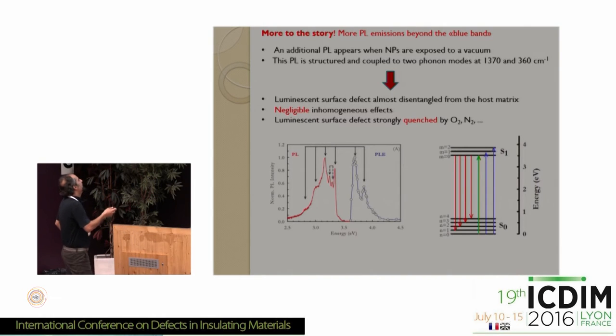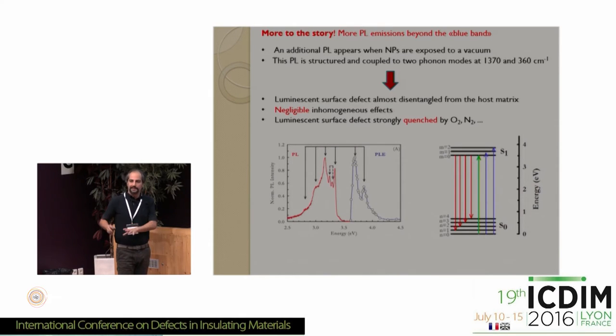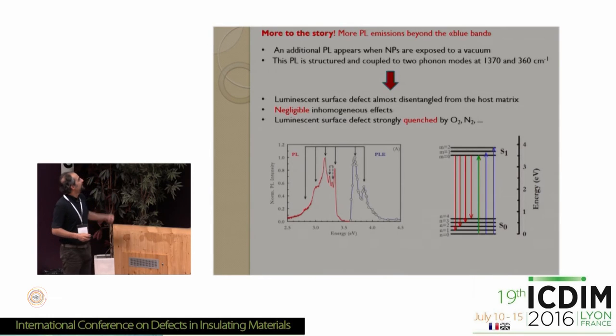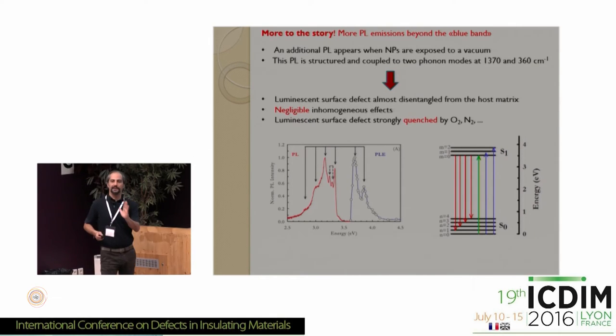And as you can see here, it's a luminescent signal which is structured. It has a certain number of peaks, which are indicative of coupling of the electronic transition to phonon modes at some specific frequencies. Right now, we have no idea what the chemical structure responsible for this luminescence is, but this is another signal which, for one, is not present in bulk silica, so it's peculiar to the nanoparticles, and also it has completely different properties as compared to the blue band, because the fact that you can observe this vibronic structure so easily means that you have a very low inhomogeneous width, because otherwise this structure would be wiped out. So this must be some kind of defect on the surface, which is more or less disentangled from the bulk, the core of the nanoparticle.